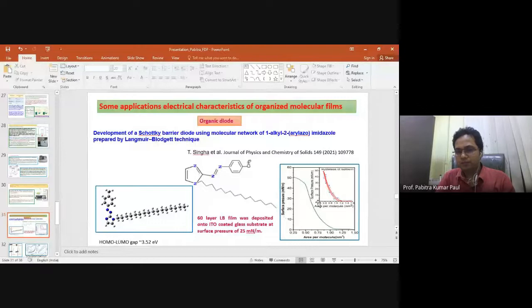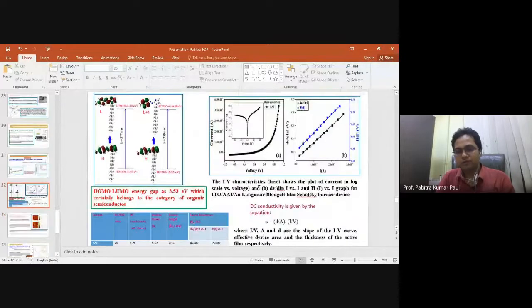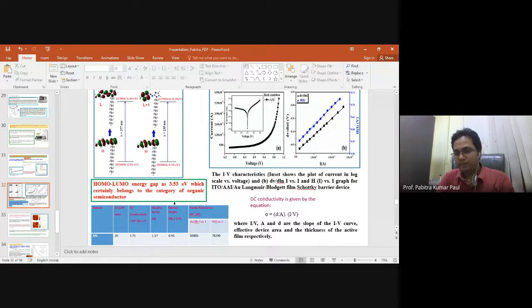And this is a 60 layer LB film deposited on the substrate, and we found this type of Schottky behavior, and the DC conductivity has been calculated. The barrier height and the barrier potential, all these are explained, and also this HOMO-LUMO gap is correlated with the current conduction, and the ideality factor is also defined. So this diode has been fabricated with the help of this technique.